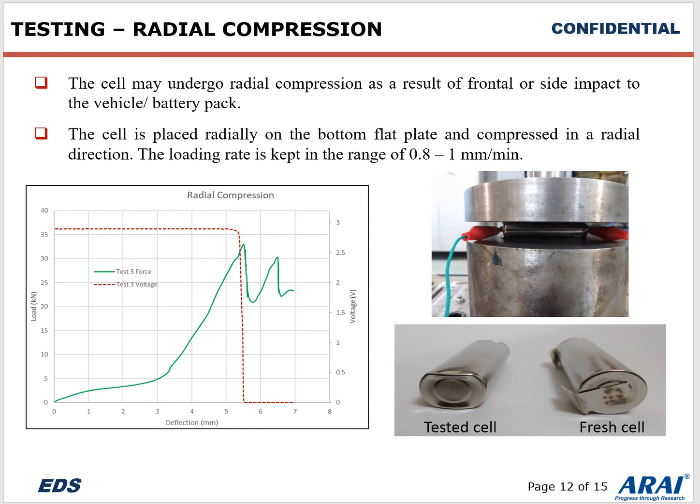This type of pattern, where the load drops and at the same time the voltage also drops, is observed in all other tests. You may consider semicircular indentation, flat circular indentation, or 3-point bending. In all tests, the same kind of pattern was observed. So we tried to correlate only the compression test with our simulation. Next we'll go for the simulation we carried out and its correlation.